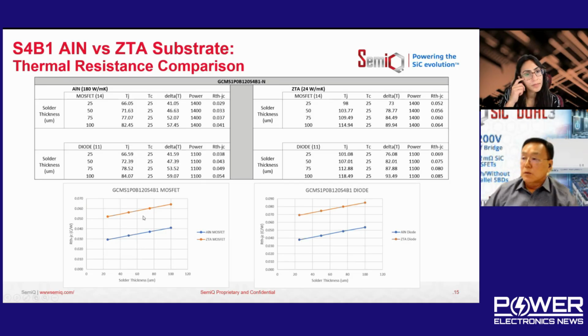So by doing that, even under the same power loss condition, you can reduce the junction temperature of the chip by another 20 degrees C, running cooler. Or if you want the same junction temperature, it can carry more power. So it's about a 28% improvement in power carrying capability. That's quite significant.